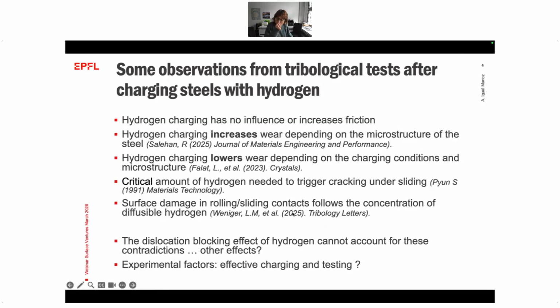And recently also our colleagues from Luleå were working with rolling sliding contacts, and they had a similar approach to the one we have here. They observed that the surface damage follows the concentration of the hydrogen diffusing in the material. So in the end, the classical hypothesis of the dislocation blocking effect of hydrogen cannot explain all the observations.